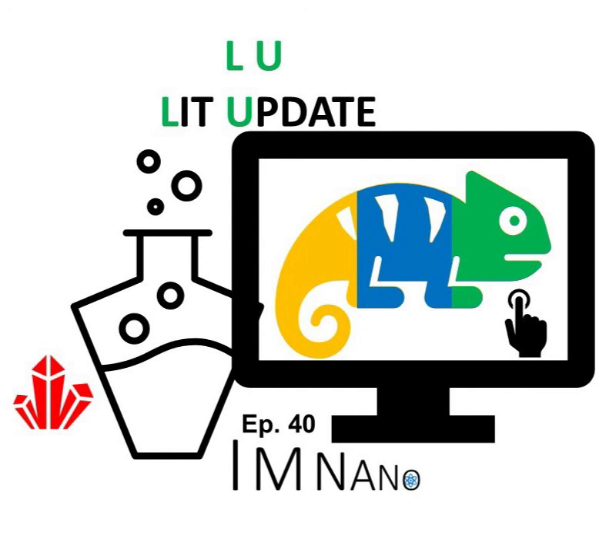Yeah, that's crazy. And so overall, nematic liquid crystals display an odd mix of fluid and solid-like behavior, and a ferroelectric nematic liquid crystal is a bit more organized, so a little organized level above that. So within specific patches or domains, all of the molecules in the ferroelectric nematic LC point in the same direction. And this phenomenon is known as polar ordering. And now this behavior was discovered in an organic molecule known as RM734.